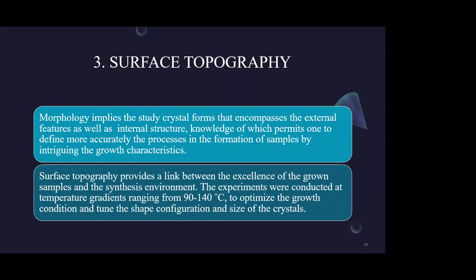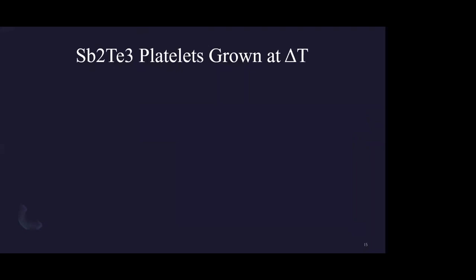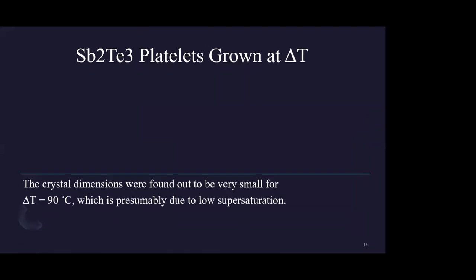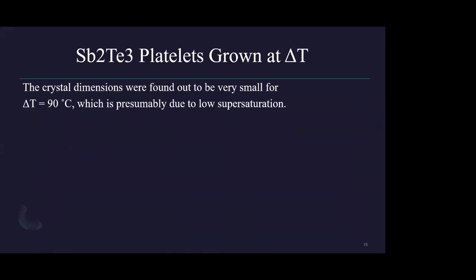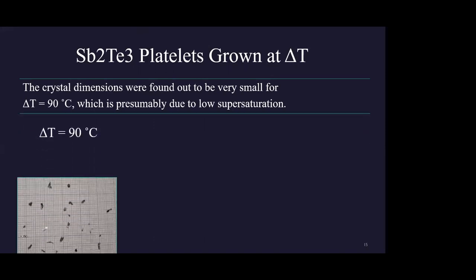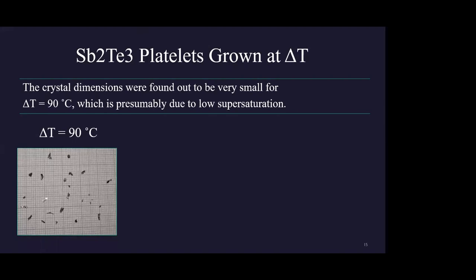gradients ranging from 90 to 140 degrees Celsius to optimize the growth condition and tune the shape, configuration, and size of the crystals. And the Sb2Te3 platelets grown at different temperatures are depicted here. To see, at 90 degrees Celsius, it is very, very small. I found that it's due to low supersaturation. This is the crystal that is formed at a temperature of 90 degrees Celsius.